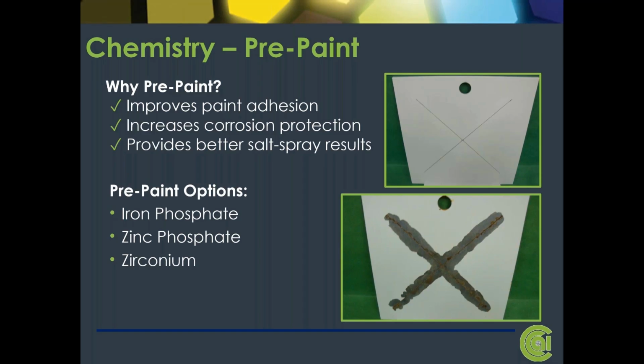The panels on the right here show they're at the same step in the process. They're the ASTM D1654 paint adhesion step. The part at the top has had a good zirconium pre-treatment. The one at the bottom is just a simple iron phosphate process. And you see the difference in the paint adhesion at the same amount of hours. Your paint is flaking off on the bottom where it's not on the top.